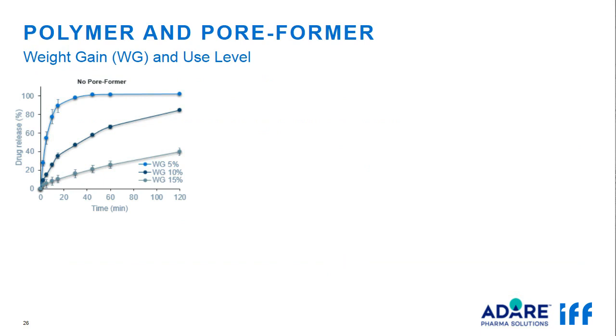The graph shows the dissolution of granules coated without pore-former at 5, 10, and 15% weight gain, and cured for 4 hours in an oven. It is shown that the drug release rate decreases as coating level increases from 5 to 15%. Without pore-former, it's more challenging to modulate drug release accurately and flexibly.